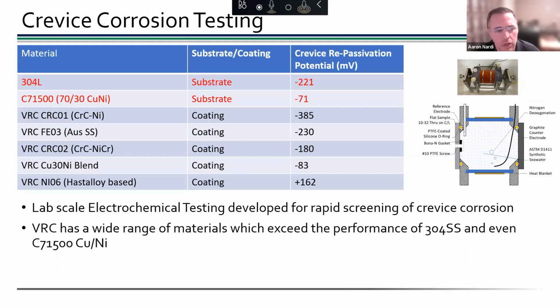We also did some corrosion work, and this is primarily crevice corrosion. So you can see the little setup here. It's a potentiostatic sort of setup. And in comparison to two materials, and this was again Navy work, so these are two materials that the Navy likes to use, 304 stainless and a 70/30 copper nickel. Now, keep in mind, more negative is going to give you more pitting, more damage of the part. So we want a more positive number, ideally. So what we can see is the 304 is that negative 220, copper nickel's that negative 71.